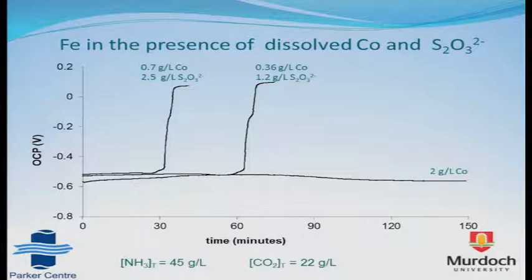The other case in which passivation was observed was when both cobalt and thiosulfate were present in the solution. You can see here in the lowest line, when there were 2 grams per litre of cobalt, the iron remained active, and that's quite a high concentration of cobalt, and still it didn't have a similar effect to the copper. Whereas when both cobalt and thiosulfate were present, even at much lower amounts and even at the typical concentrations found in the Caron process, you get a transition to the passive region.